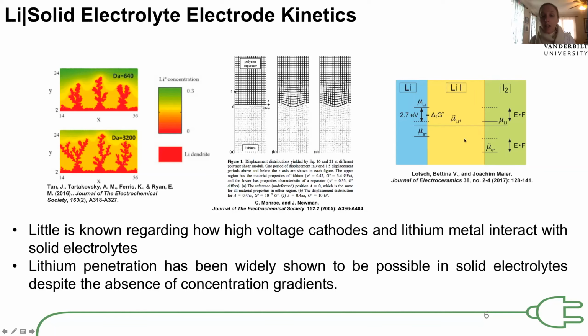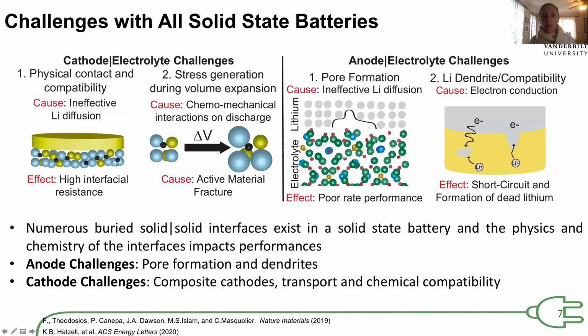Mainly, you have a solid electrolyte that resides at a chemical potential, and this chemical potential is most likely going to be different than the anode and cathode. And that can drive chemical decomposition as well as irregular interfaces that make, in particular, plating and stripping lithium metal very challenging. In addition to those problems, we can have chemomechanical stresses that happen in the cathode over charge and discharge, and that can lead to non-uniform stress generation. We can also have the formation of pores if we strip the lithium metal too quickly, where we can't overcome mechanics, and we can form these voids or pores at an interface. And both of these challenges we don't know much about, primarily because these exist at buried solid-solid interfaces.